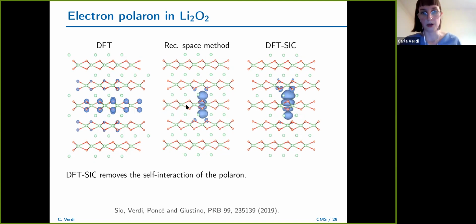We proposed a way to eliminate the self-interaction in DFT for the polaron. And if we do that, we obtain this very, very similar wave function. And this is also validation of our method, of course.